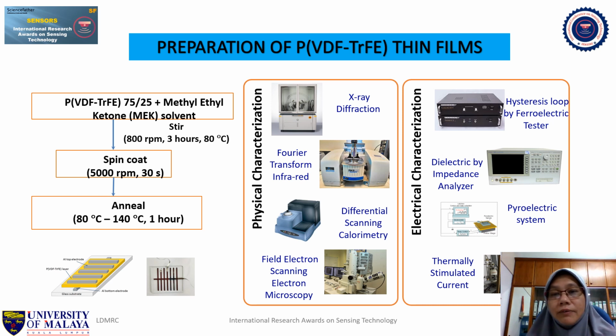The PVDF-TrFE thin films are prepared following this flowchart here. Initially we dissolve PVDF-TrFE with methyl ethyl ketone solvent, spin coat at 5000 RPM for 30 seconds, and then anneal at temperature between 80 to 140 degrees for 1 hour. This picture here shows the sample that has been produced as thin films. Here is the top electrode and the bottom electrode is here, and the yellow color represents the thin films.